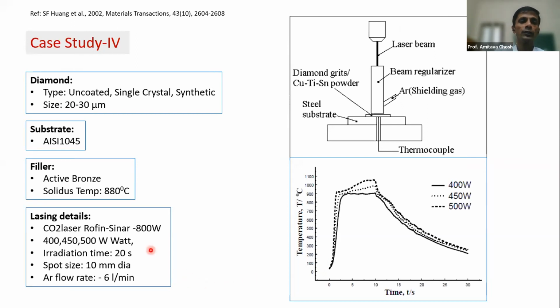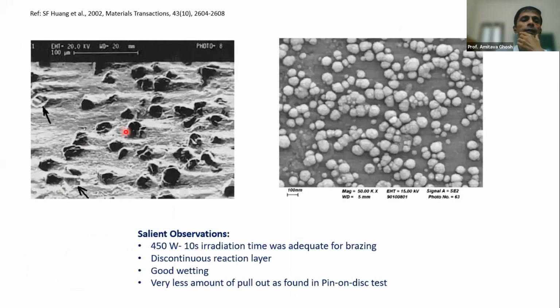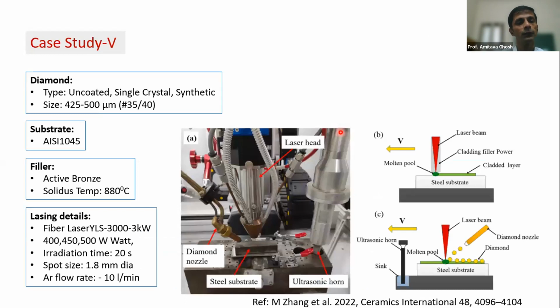This is again a CO2 laser, which is used just to see the effect of different wattage. And again, it was done in the argon atmosphere. It has been observed that the grits, the abrasive particles, are quite well retained on the substrate matrix. And the reaction products at the interface are the same, like titanium carbide, a little discontinuous layer, which is good for reduction of the residual stress. But at the end of the day, when the joint strength was tested, it was observed to be adequate for the purpose it was made for.